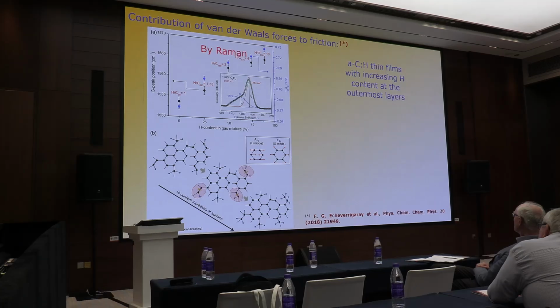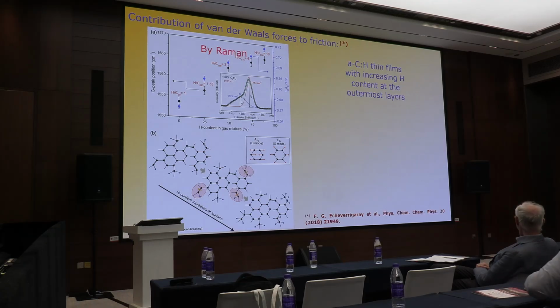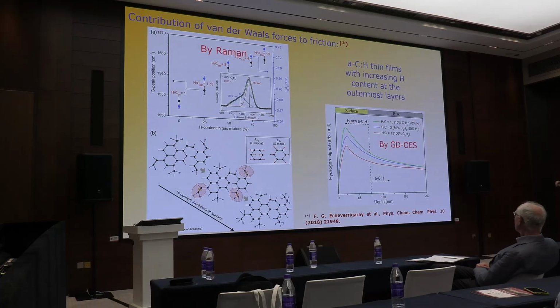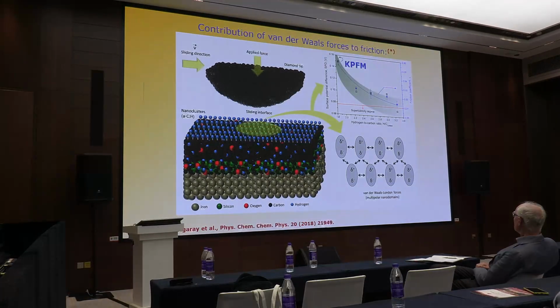Here we started another set of samples with carbon, but DLC, amorphous carbon, with different content of hydrogen. Okay, this is characterization. We use different content of hydrogen in the plasma to deposit the thin film, and we could see that when we use more hydrogen in the plasma, we have more hydrogen at the surface of the thin film. Okay, no problem. The point is we have different thin films with different content of hydrogen on the surface or in the outermost layers.